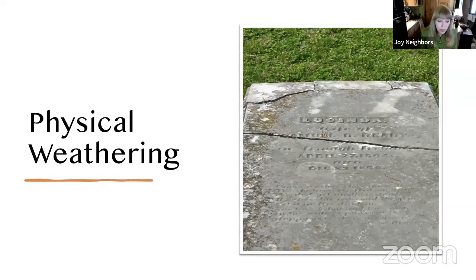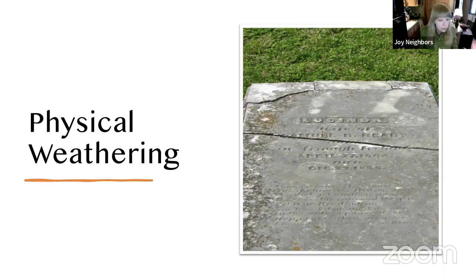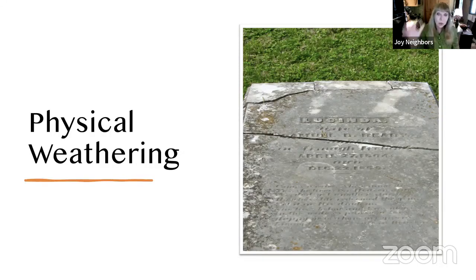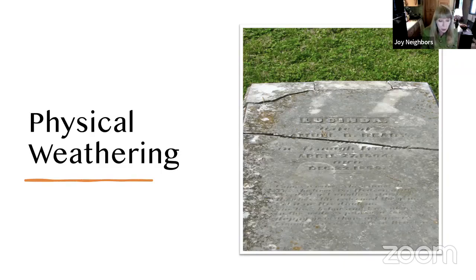The expansion-contraction weathering has the opposite effect but the same result. The outer stone surface expands during hot dry days and then when it cools rapidly at night, it creates stress on the marker, leading to fissures and cracks — especially in locations like the southwestern United States.